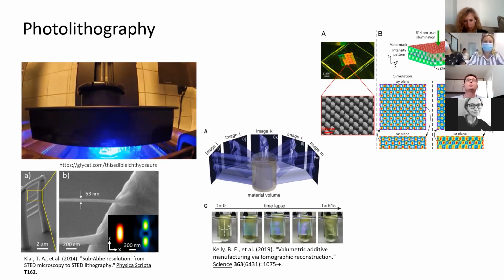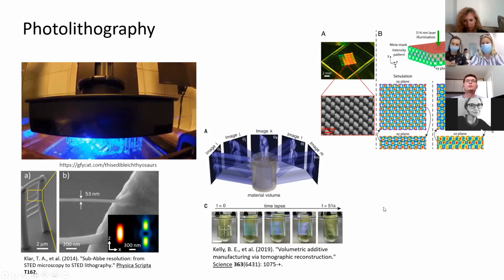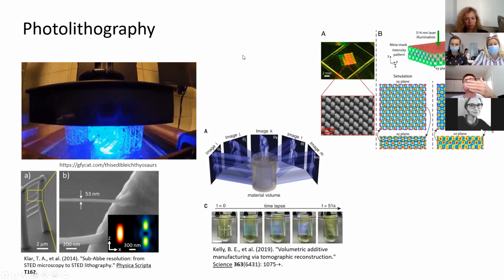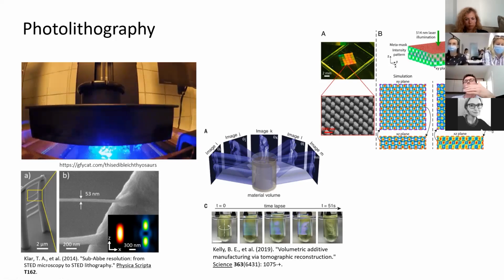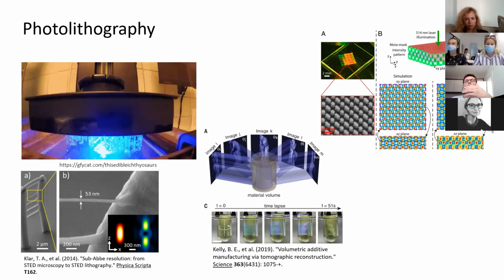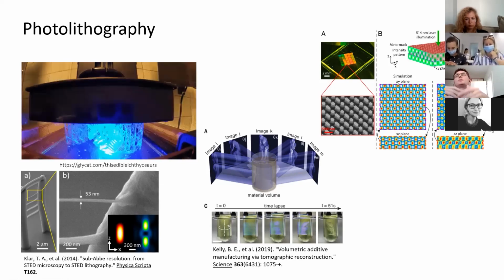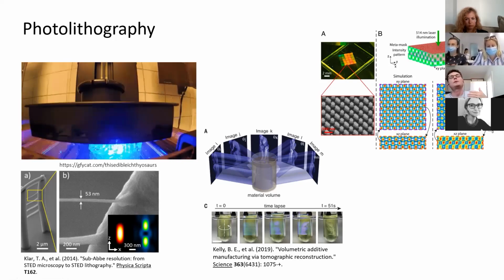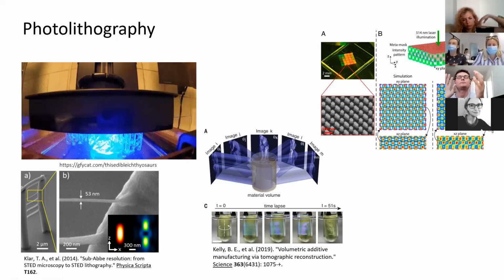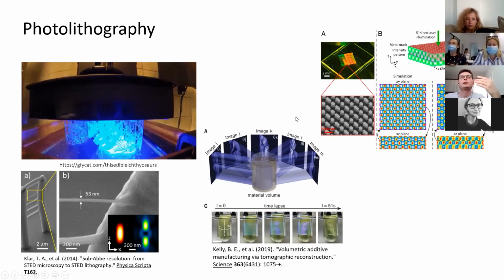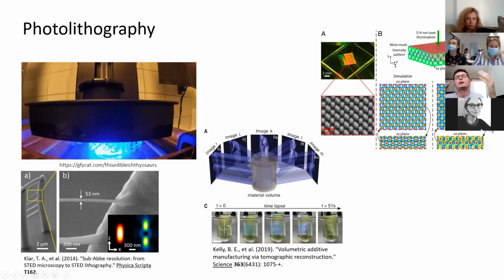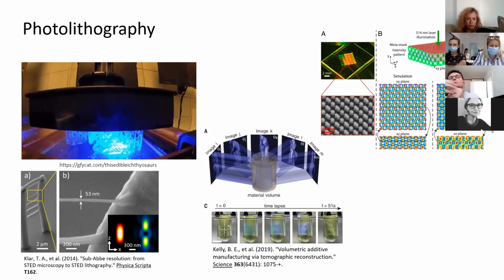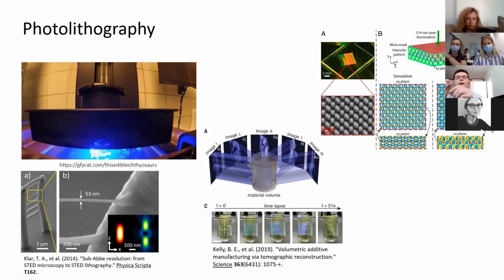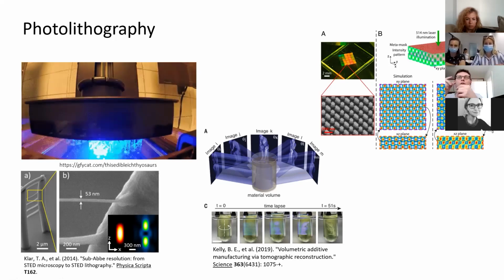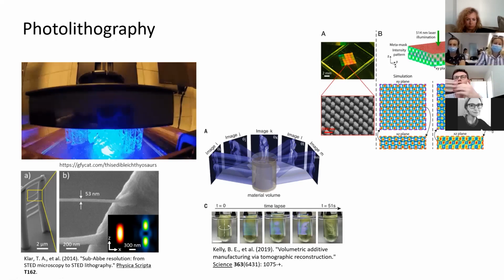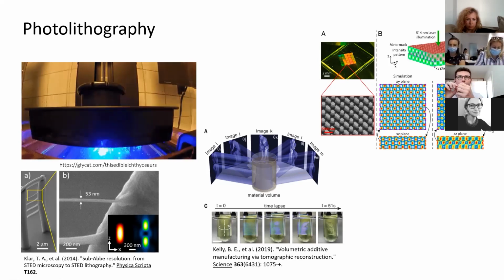Then there are also other lithographic techniques that have started to develop fairly recently. Interesting is volumetric bioprinting. There you don't have a focused laser that causes the polymerization, but the polymerization is the product of temporal superposition. You have a container with the resin that is rotated slowly, and you project the image with different intensities, and only where the intensity accumulates over time appropriately do you have polymerization.